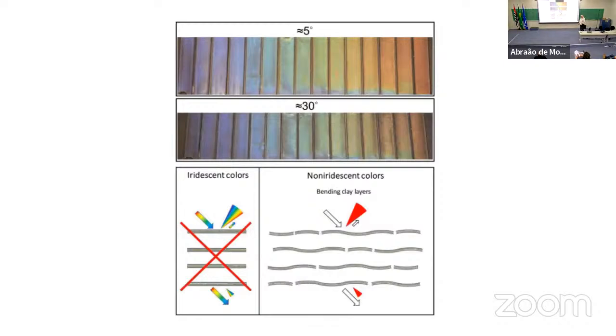Another interesting issue with our structural coloration is the non-iridescence. The color doesn't change with angle. The reason is that the clay platelets bend a little bit. And this is built into our system. We don't have to do anything particular. The clay platelets just bend. They are not stiff. So we get angle-independent coloration.